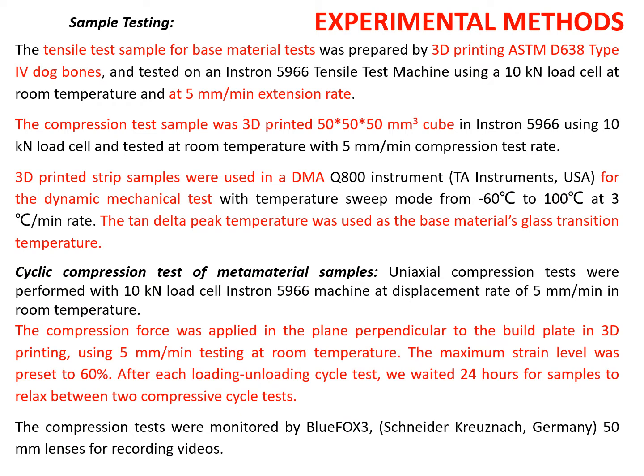The tensile test sample for the base material test was prepared by SLA process, printing the ASTM D638 type 4 dog bone samples, which were tested under 5 mm per minute extension rate. The compression test samples were 50 cubic millimeter samples simulating the lattice structure, and these were tested under compression. And 3D printed samples were also prepared to use in dynamic mechanical analysis. The tan delta peak temperature was used as the base material's glass transition temperature.